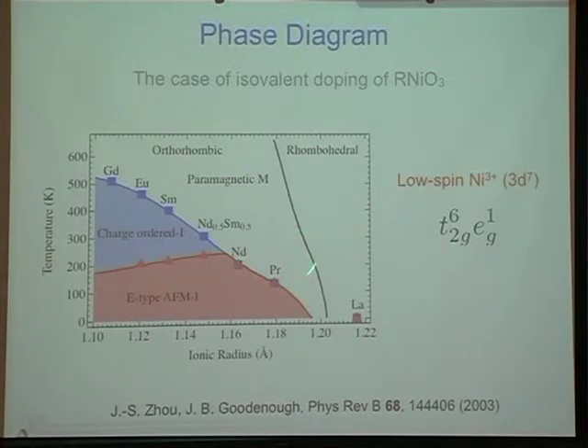And if you're over here, if you have lanthanum, it's rhombohedral and metallic and paramagnetic. As you go this direction, in terms of shrinking ionic radius, what happens is you lower the symmetry to orthorhombic, and at the same time, once that happens, you start to have this first-order metal-insulator transition.